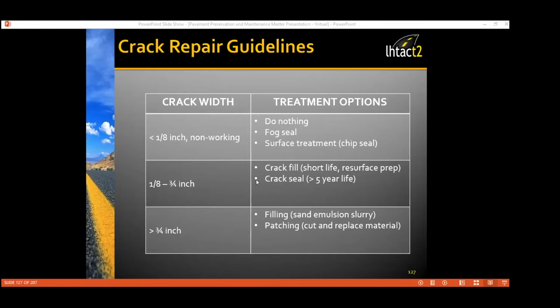If they're between an eighth of an inch and three quarters of an inch, crack filling is an option. We can use crack sealing. We might get a good service life from that crack sealing, maybe approaching 5 years. If the crack is three quarters of an inch or larger, probably filling those cracks with some kind of a sand emulsion slurry might be a good idea. And patching, where we have to cut and replace the material, would be a good option for those larger cracks.